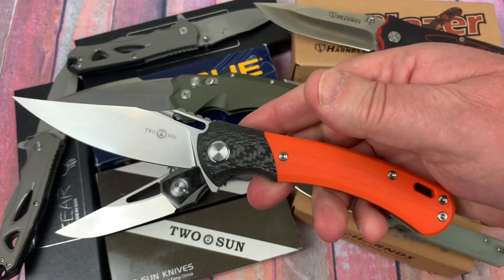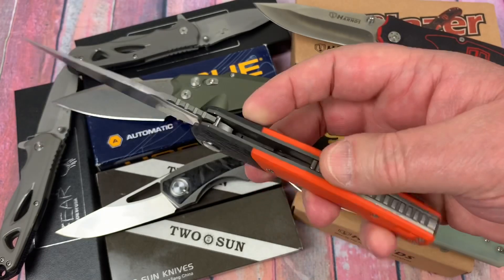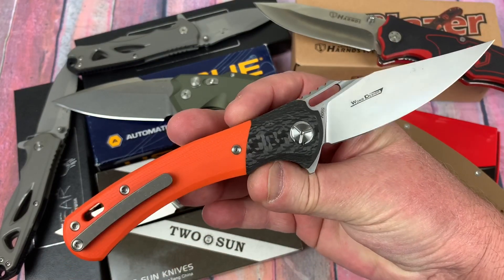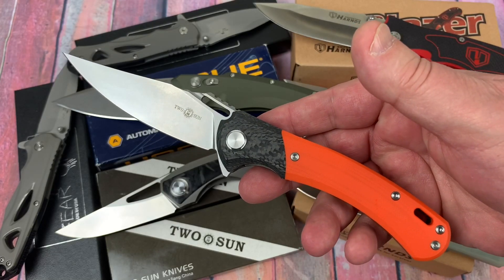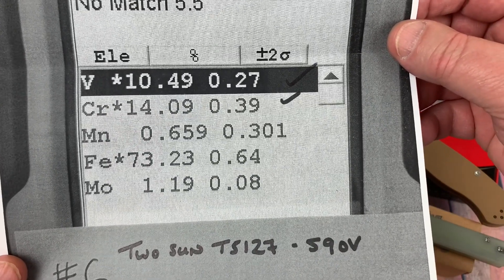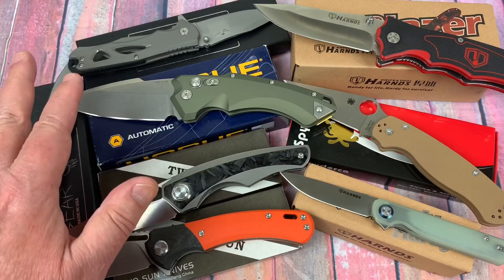The last one is my Wolf Fish — a Wong design. I never get names when I buy a Wong knife; I'll message him through Instagram and he'll come up with a name. This is the Wolf Fish, and it's in S90V. They also made this in Sandvik as a Two Sun model — the TS-127. But this is S90V. Look at the vanadium — ouch, that's really good. Yes, it's real S90V — that's solid. And it's a 58.2 HRC. Could it be a little harder? Maybe. But it's still in the zone and it's good. The Two Sun knives I've checked are all true to the blade steel they advertise.